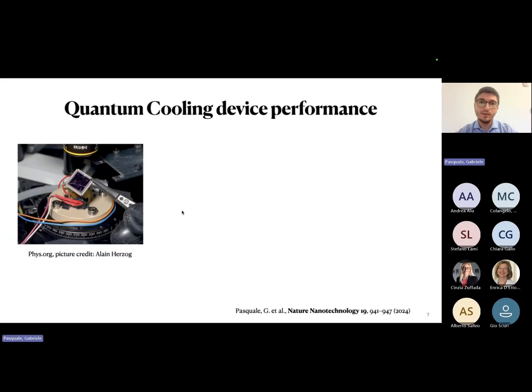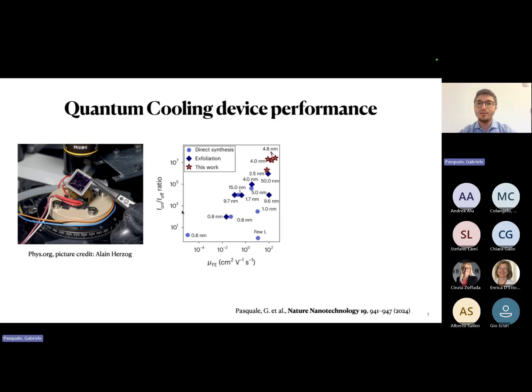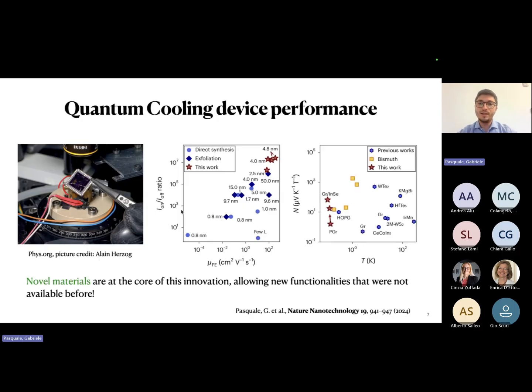This is very interesting, and we can think about the device performance. When we decided to quantify this, we first compared to the literature the electrical performance, which turns out to be very good, but also the thermal power conversion performance, which is not only record high for those ultra low temperatures, I'm talking around 100 millikelvin, but can also be largely tuned with electric field. Therefore, the point I'm trying to make is that novel materials are really at the core of this innovation. We cannot decouple a tool that we are using now as a quantum cooling device from the two-dimensional materials that are really at the backbone of this discovery.